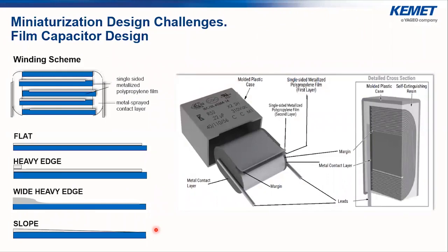So let's go a little bit into the construction of the film capacitor and the challenges which we faced during the miniaturization and how we got there. So you know, there's a considerable amount of material science involved. Just to review briefly, a film capacitor is basically a wound element of metallized polymer film, for safety capacitors most probably polypropylene. That's really because it has excellent electrical properties and self-healing capability. The metallization is usually some type of aluminum zinc that can be flat, heavy edge, or wide heavy edge on the slope, which forms the electrodes of the capacitor. Then the capacitor is put in a plastic box for protection, and this plastic box is filled with some type of potting compound to mechanically stabilize the component and also to provide environmental protection for the capacitive element.